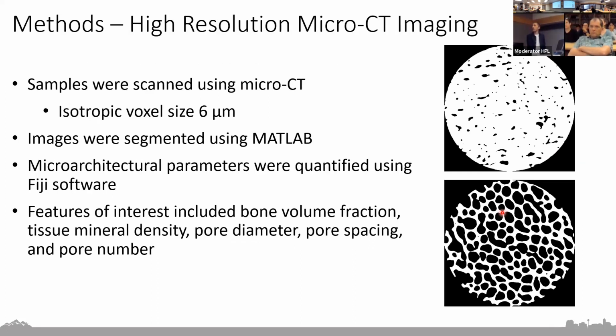Next, we used some high resolution micro CT imaging on our samples. We scanned with a voxel size of 6 microns and then segmented our images using MATLAB and quantified the microarchitectural parameters using Fiji. So a few of the things we looked at were bone volume fraction, tissue mineral density, and then pore diameter, spacing, and the number of pores.